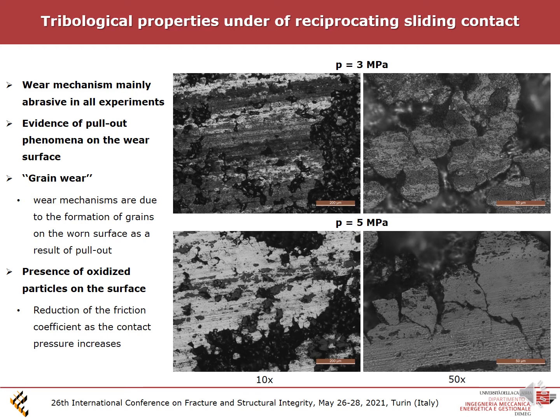Grains, in fact, are typically formed after wear tests for thermal spray coatings and generally are responsible for a type of fatigue wear named grain wear, consisting of pulled-out particles that form small flattened oxidized debris on the wear surface.